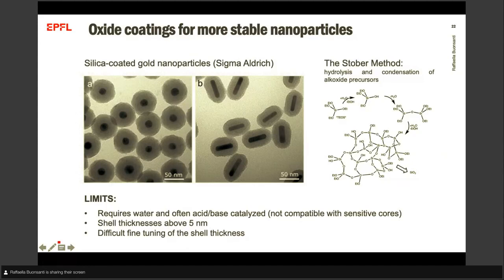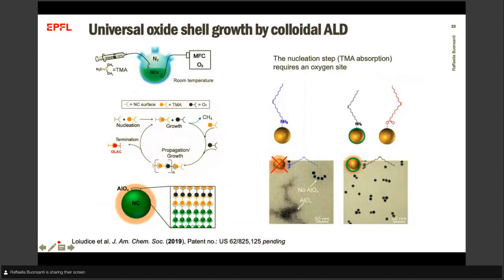So what my postdoc Anna did was to develop a colloidal ALD approach, which is very similar to gas phase ALD, but occurs in solution. So we have our nanocrystals in solution, and we add sequentially the trimethyl aluminum and the oxygen in solution. So we reproduce basically the same cycle that I showed you a few slides back. We also looked into how nucleation occurs, but I'm skipping this part for this talk.